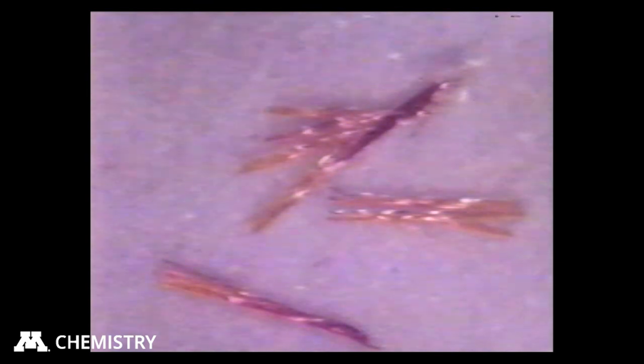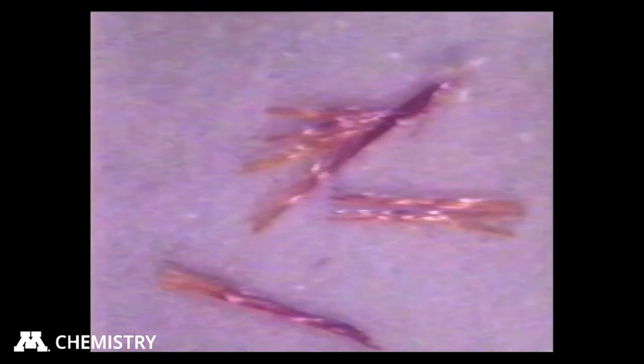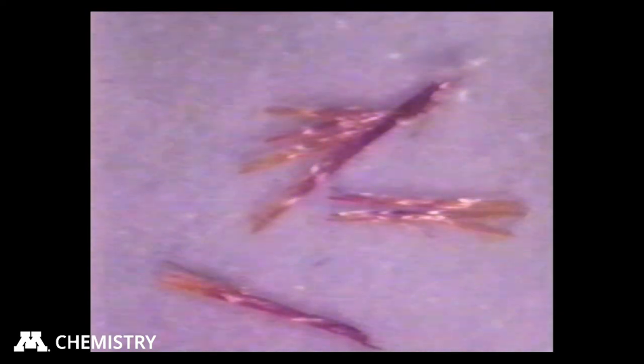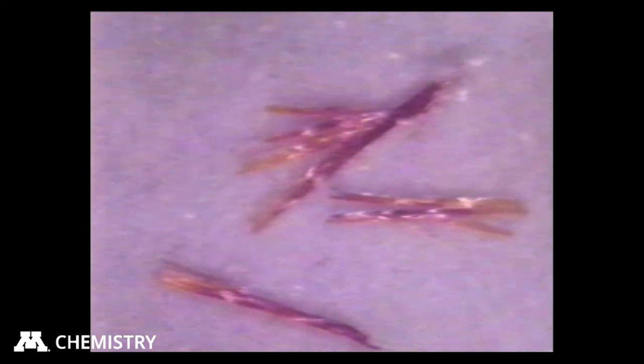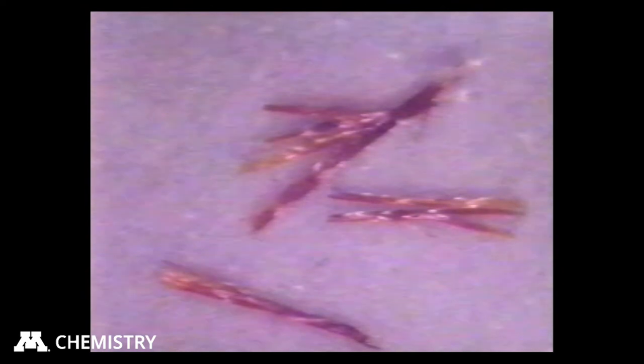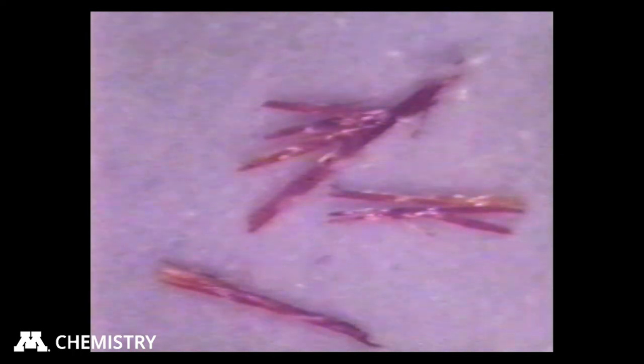And if you can watch one crystal at a time, it will look almost like a liquid running down the crystal. So these are basically unidirectional phase changes in most of the crystals we look at. So they're anisotropic, and this is one of the interesting parameters of solid state chemistry that you don't have with solution chemistry, and that parameter is direction. In many cases you have reaction directionality in crystals, and we're seeing an example of that here.